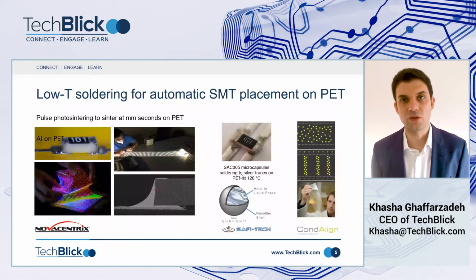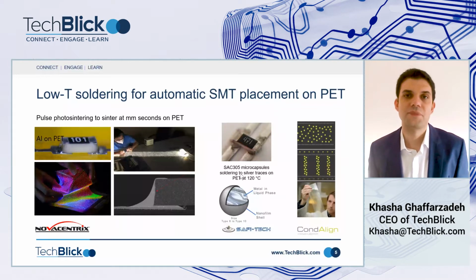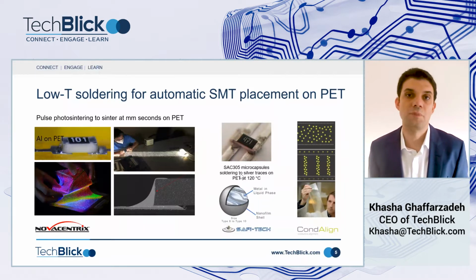However, now there are some very, very interesting approaches that allow one to solder on substrates such as PET. One of the interesting approaches is by our gold sponsor, Novacentrix. And what they do is they are bringing their pulsed lighting system into soldering. So you can expose the solder joints to a high dose, a pulsed dose of light, and that will allow it to form the joint without the actual substrate experiencing a high temperature. And what is even more interesting is that this process, if the sintering profile is optimized, can take place in a matter of milliseconds. So it means that you can really solder roll to roll at high throughputs on substrates such as PET.